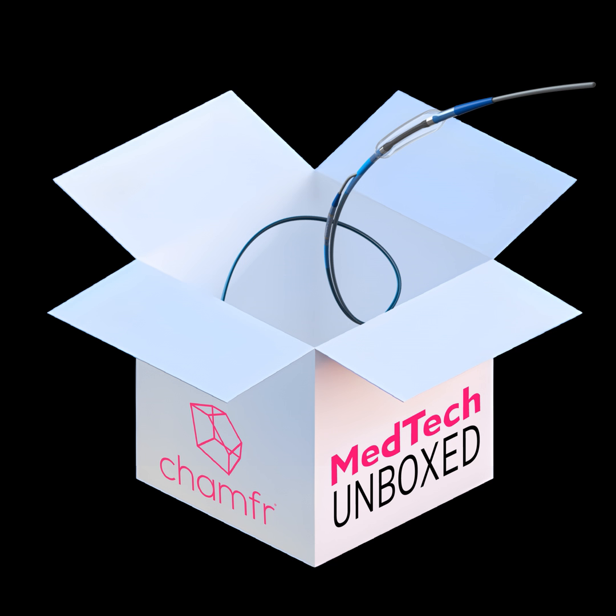One of the major things we do there is we employ vacuum venting on a lot of our tools. So we'll intentionally, behind those match lines, connect those match lines and those vents to an enlarging set of plumbing, basically, and pull vacuum on that to empty the cavity of air as soon as the main mold halves close and effectively seal. We're then evacuating the cavity of all the air. And then while the shot is going in, those few milliseconds, honestly, that the fill happens, we're pulling any gas that's at the flow front out through those vents with vacuum assist.